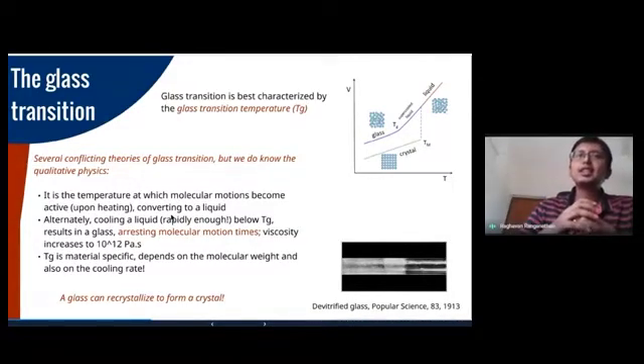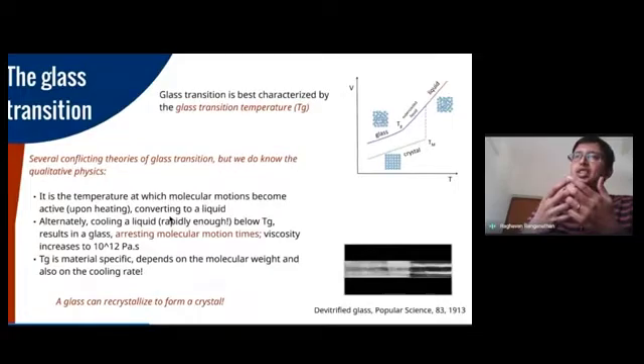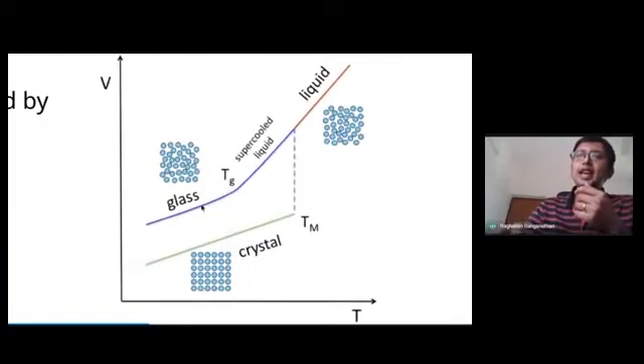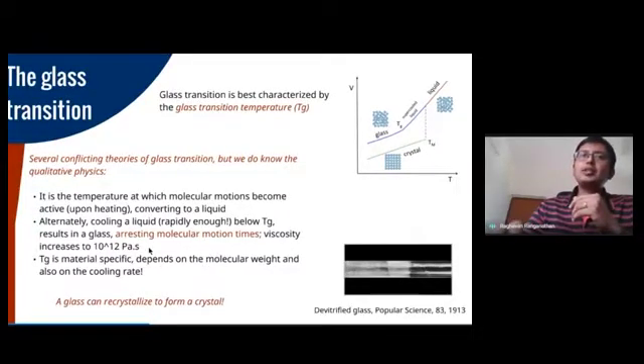Okay? So the first thing is the temperature upon which the molecular motions become active or inactive. That is really characterized by Tg. So what I mean by that? So if you take a glass from the low temperature and start heating up gradually, you increase the temperature. Okay? You will encounter the Tg, the glass transition, above which the atoms now have sufficient energy because they are at sufficiently high temperatures, and they start exhibiting rapidly evolving atomic motions. And essentially, they get transitioned to a liquid state. So Tg basically governs where the atomic motion is arrested. So is it a liquid or is it a glass, right? That's what Tg demarcates.